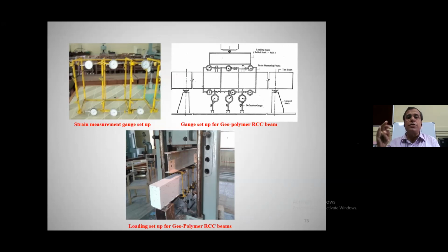Moment versus curvature relations we can get experimentally. The same curvature we also get theoretically. We can compare these two for the same grade, same geometry. That is experimental, this is theoretical. If these two values are really intersecting or really cohesive, nearer values, then you can say that your methodology is correct. This is how you can plan, and this is the beam, how it is kept at the top and bottom, and we have tested the beams.